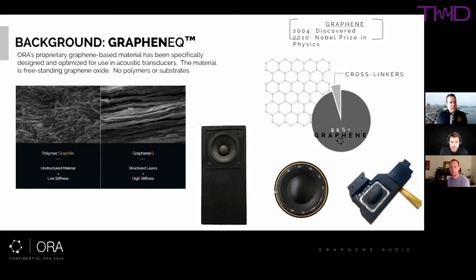Okay. What's the total thickness of a headphone driver membrane? Well, currently we can deposit between about 10 microns and about 200 microns thick. Okay, I believe a typical headphone driver membrane is about 35 microns. Right. It's very thin. It is, and it can be a little bit brittle to handle. We have to work with our supply chain to train them to be able to assemble these drivers consistently.